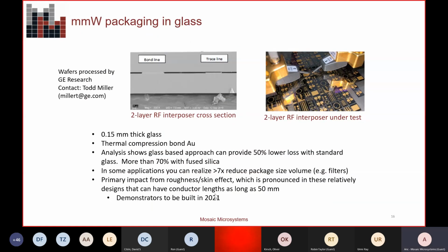And then here's another example of some work that we're doing with General Electric. This is for a DoD application for an electronically steerable antenna in the Ka band. And GE was able to leverage our process to do 2 things that I've talked about. One was to thin the TGV wafers down to 150 micron. So they did this both in the willow glass and the fused silica. But for the fused silica, they were able to leverage our process to get the wafers down to 150 microns thick. And then they did the metallization. They put the structures on the wafer and then bonded 2 of the wafers together with thermal compression gold. And so this work is ongoing through a phase 2 effort, a larger effort to actually make these steering antennas in the Ka band.